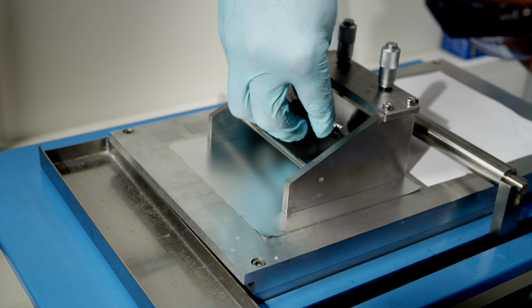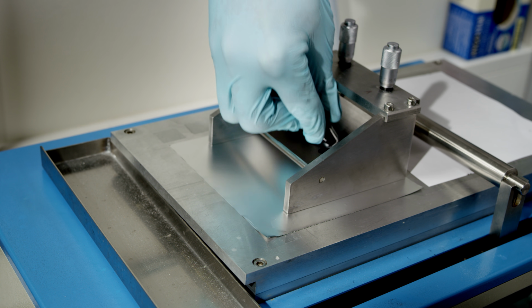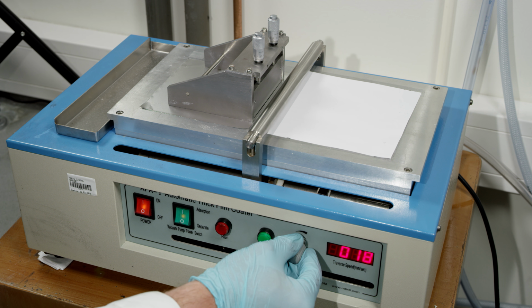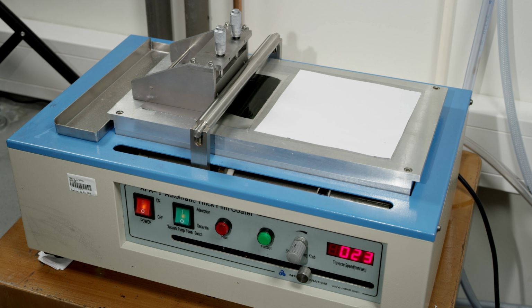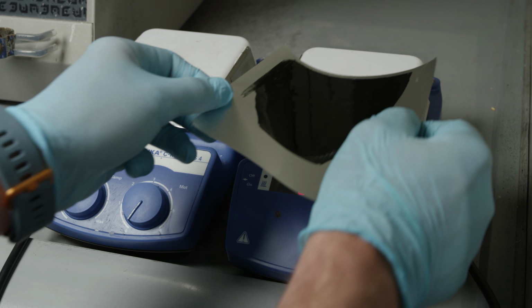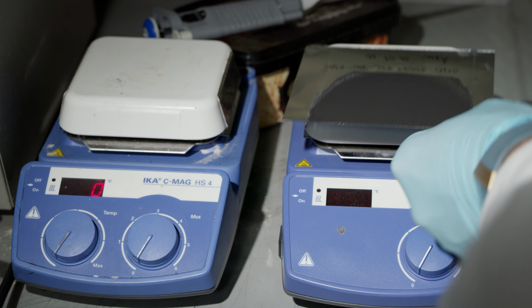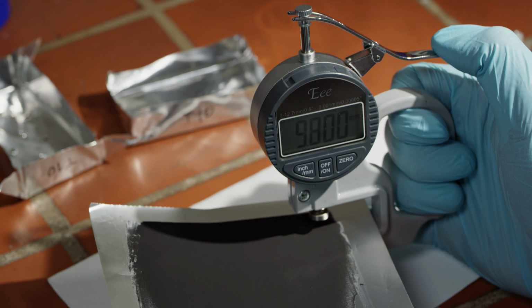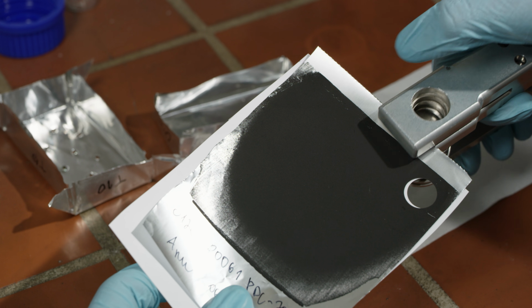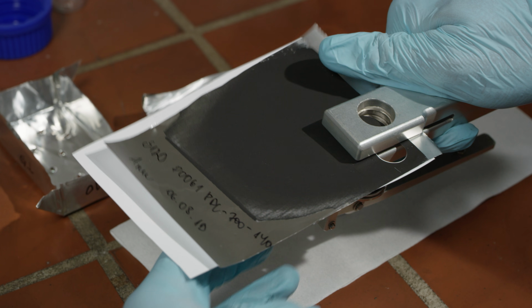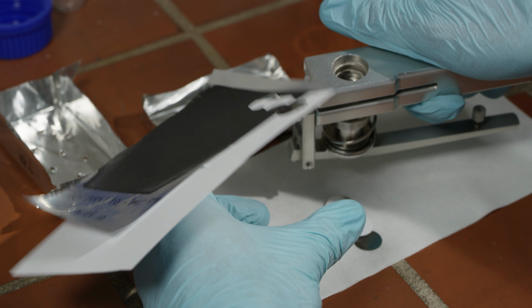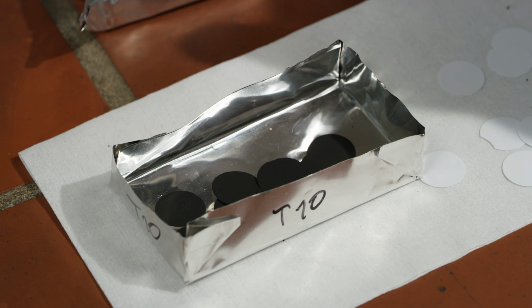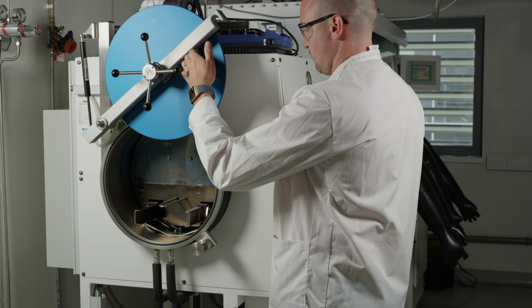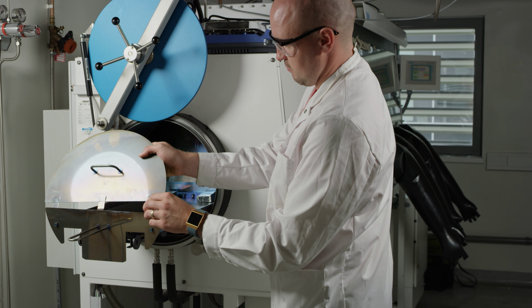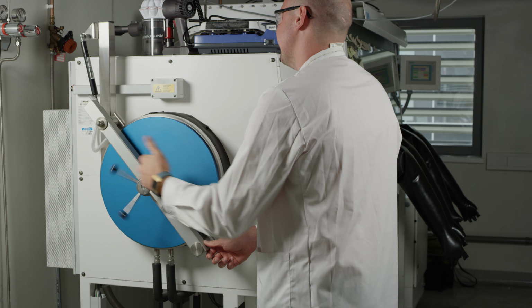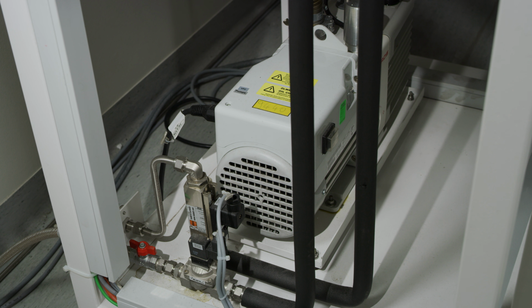Then the electrode slurry is cast onto the aluminum foil. A device called a doctor blade is used to make sure that the coating is even on the surface. Then the electrode is dried to evaporate the solvent. Once it's dry, it's measured for thickness and consistency, and then the electrodes are cut out of the current collector in proper size for the next step. Next, they're put into a vacuum furnace to dry the electrodes completely to get rid of all water that can be trapped inside because the battery is very sensitive towards water.